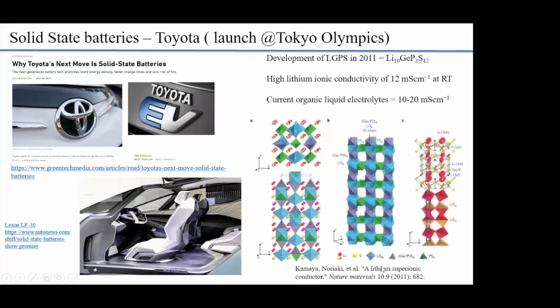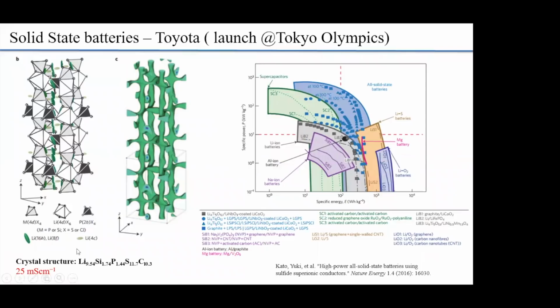So they published this paper called A Lithium Superionic Conductor, and they proceeded to develop more on it. In 2016, they improved upon it. So they had lithium, silicon, phosphorus, sulfide with some chlorine doping. And that had a remarkable ionic conductivity of 25 millisiemens per centimeter. That is remarkable for a solid electrolyte. So as you can see, this is the skeletal structure. And then within the skeleton, you have lithium. The green structure shows where lithium can go. So you can see long pathways, which provide a wonderful connected pathway for lithium to go from one side to the other. So that's why they call it a super ionic conductor for lithium.